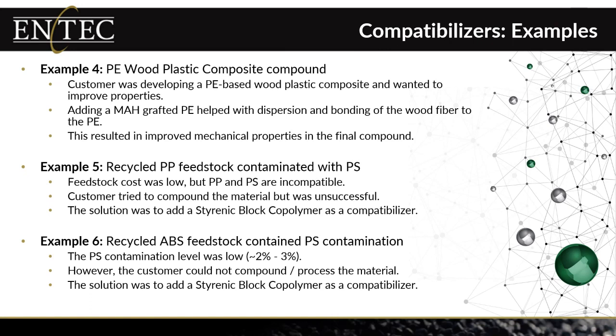And this particular customer would notice, even with very, very low levels, like 2 or 3% of polystyrene contamination, they were not able to even process the material. So once again, here's another example. A styrenic block copolymer can compatibilize that polystyrene contamination into the ABS polymer and provide a product now that has much improved properties and that you're able to process better and get better performance.